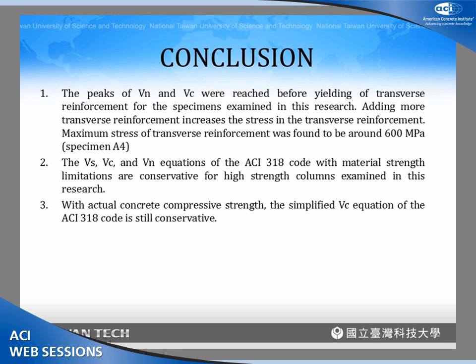The second conclusion, if you use the ACI 318 shear strength equation with all the material limitation, 70 megapascal for the f'c and 420 megapascal for the fy, you are able to get a conservative estimation of the shear strength of high-strength columns. And if you increase the concrete compressive strength to the actual, as high as 120 megapascal investigated in this research, you still can get a conservative result with the ACI 318 simplified Vc equation. For the detailed one, I still need further study to make sure we get a conservative or unconservative result.